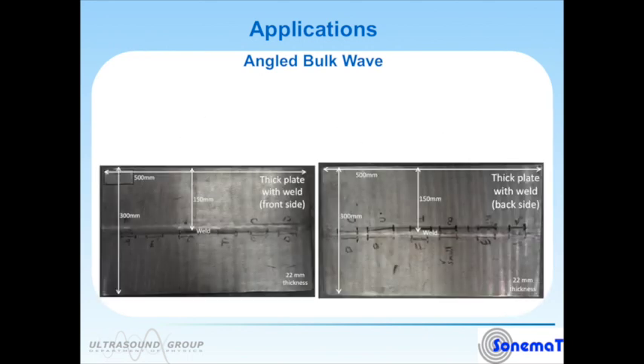The images here are of a 22mm thick stainless steel welded plate, both the front and the back of the plate. There are a number of deliberate defects manufactured into this plate. Stainless steel welds are notoriously difficult to inspect because the high anisotropy that arises in the welding process steers the ultrasonic beam into directions that make it very difficult to get the sound from the transducer to the weld and then back to the transducer.